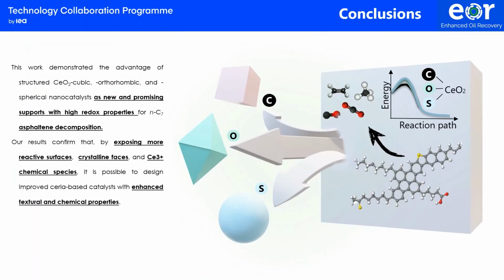Finally, this work demonstrated the advantage of structured cubic, orthorhombic, and spherical ceria nanoparticles as new and promising supports with high redox properties for asphaltene decomposition. Also, it was demonstrated that by exposing more reactive surfaces, crystalline faces, and ceria 3+ chemical species, it is possible to design improved ceria-based catalysts with enhanced textural and chemical properties.